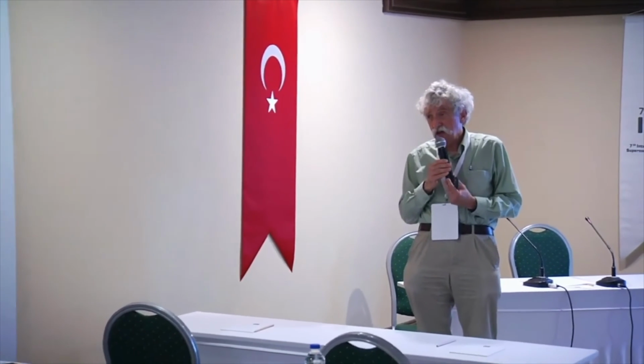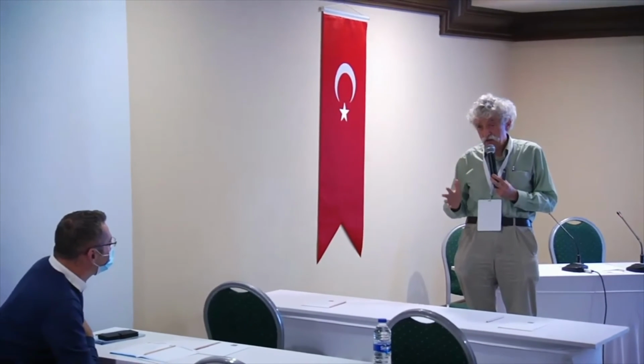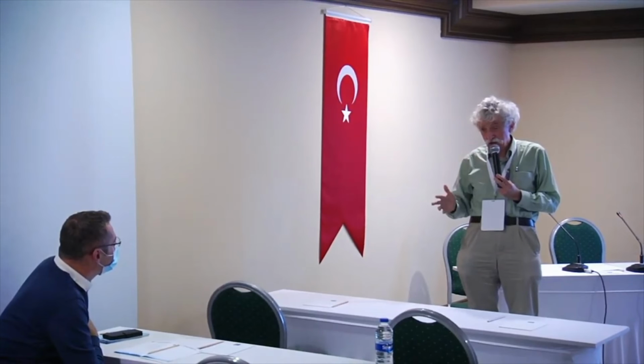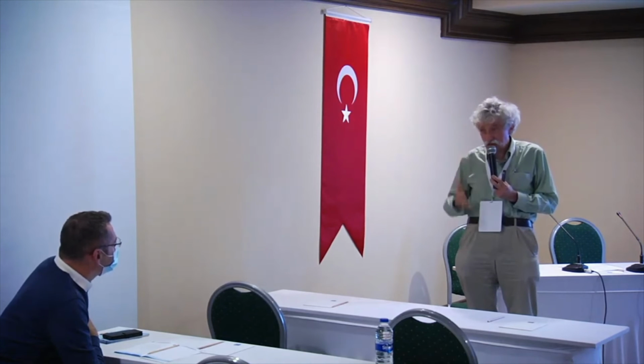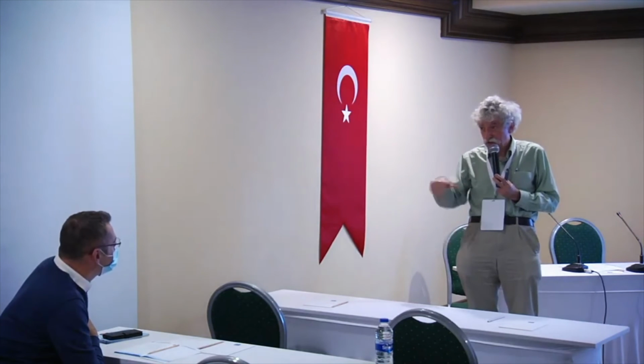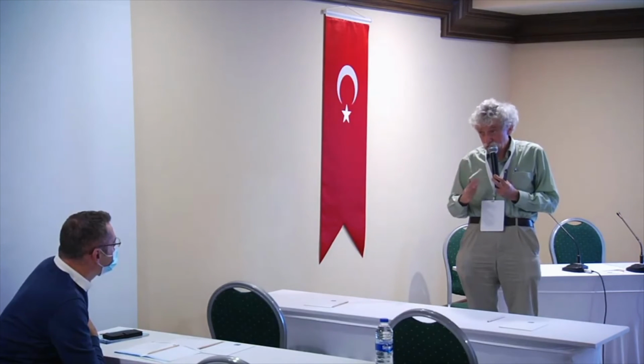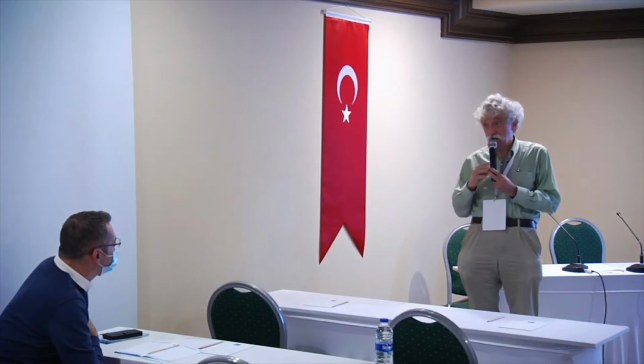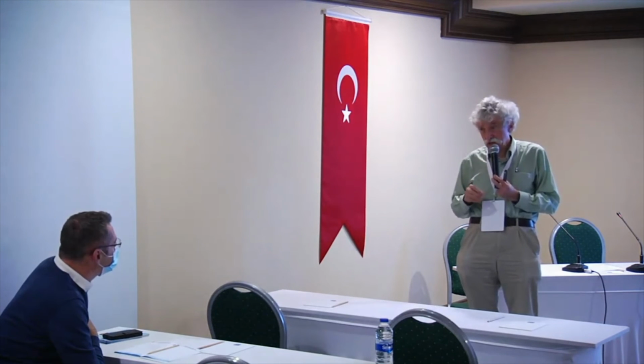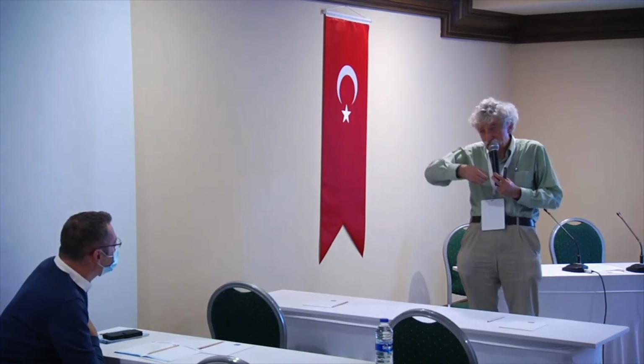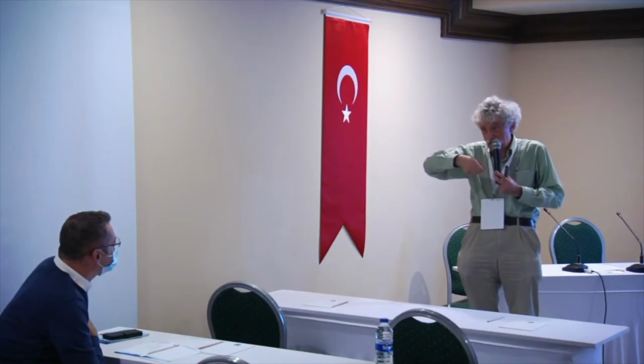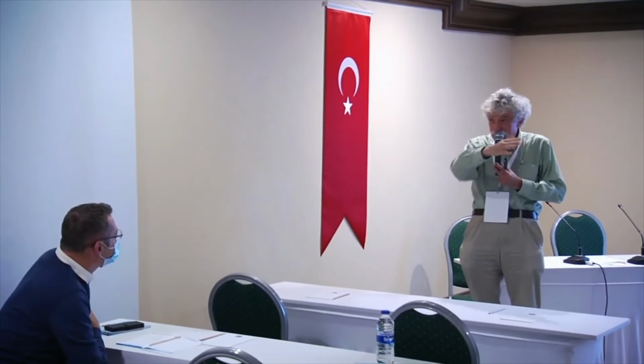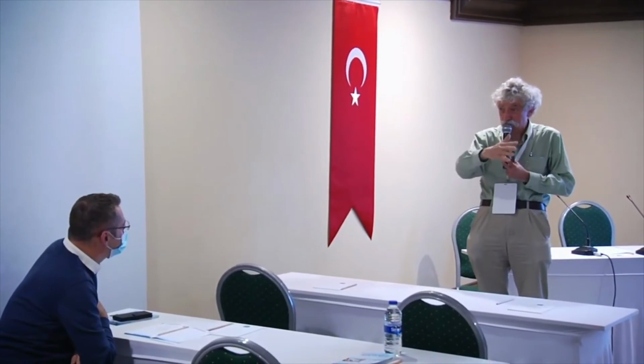And concerning your comments, I understand, but you see, for example, everyone who makes iron-based superconductors, if they make a polycrystalline sample, they have very high quality materials, with good superconductivity. But if they start to make single crystals, a lot of problems appear. So this is first, about the naive idea of a relation with quality of crystals. And still you can think that you have some inhomogeneity in the material. Not inhomogeneity, but inclusion. For example, there is hexagonal structure and tetragonal structure. So you can have some stress in the material, and superconductivity might be just at the boundary, or just because of the stress, or just because of inhomogeneity.